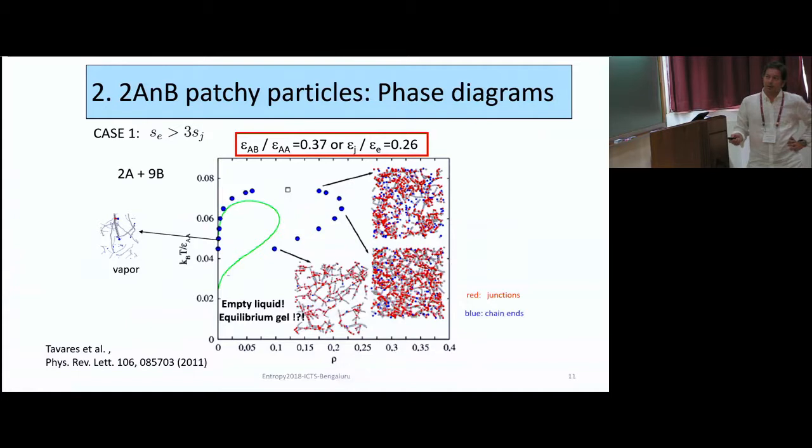But still, at low temperatures, what happens is that the liquid binodal becomes reentrant. It means that the coexisting liquid starts to decrease its density. And so here in this region, you have a liquid of very low density, so it's not a gas. The gas is really here, almost 0, and a percolated liquid, as you can show in simulations and in theory.